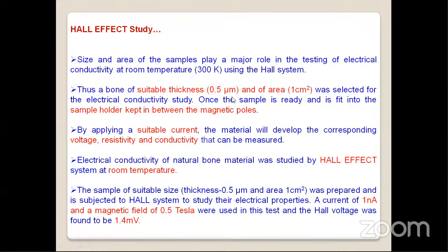The bone of suitable thickness we need to select, at room temperature, and we apply a suitable current. Therefore, the development of voltage, resistance, and conductivity, all one can measure using this Hall effect at room temperature. We are sending a current of 1 nanoampere only, a very small current, to the sample. It is showing maximum resistance, nearly resisting the current, with an applied magnetic field of about 0.5 Tesla. The Hall voltage is found to be about 1.4 millivolt. For this small current, it is developing 1.4 millivolt.